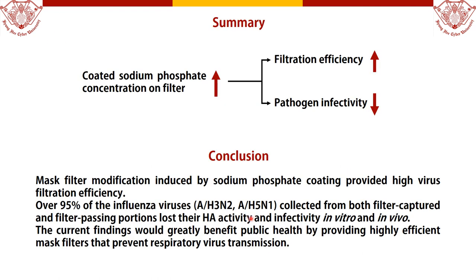The mask filter coated with sodium phosphate can destroy viruses, and as the coating concentration increased, the filtration efficiency was increased and the virus infectivity was decreased. Our findings are expected to be of great benefit to public health by providing high-efficiency mask filters to prevent respiratory virus transmission.